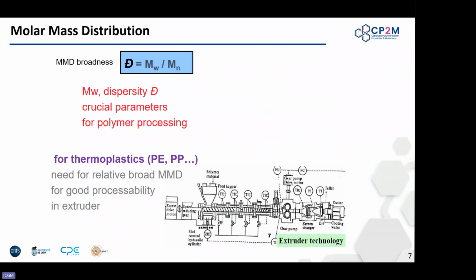So yes, a comment on the molar mass distribution. A lot of people would tell you, I do controlled radical polymerization. I want to aim at a dispersity of 1 or close to 1. Okay, if you do polyolefin, polyethylene processing, you don't want that. Basically, you want something a little bit broader, where you have high molar masses and a little bit of a tail in low molar masses that will help your processing, especially for extrusion or injection molding, for instance. Okay.